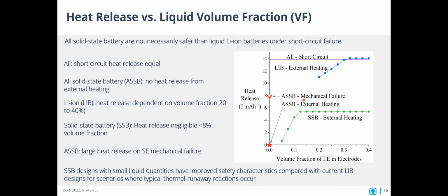This study also showed that you can have a solid state electrolyte with just a little bit of liquid electrolyte, quite a bit less liquid than you'd find in an all liquid electrolyte cell, in that under the failure of compromising either the cell casing or external heating, this solid state electrolyte would then also release less heat. But again, I think the main takeaway would be that, as people move to developing solid state chemistries, shorting through these electrolytes still poses an extreme danger.